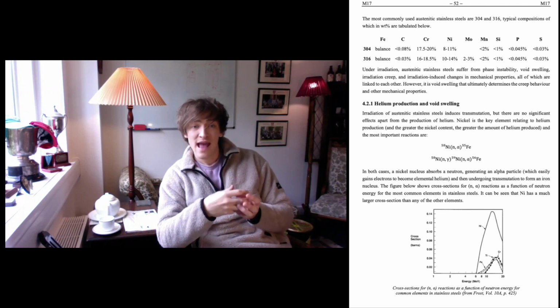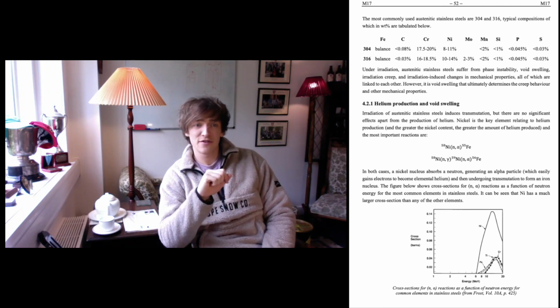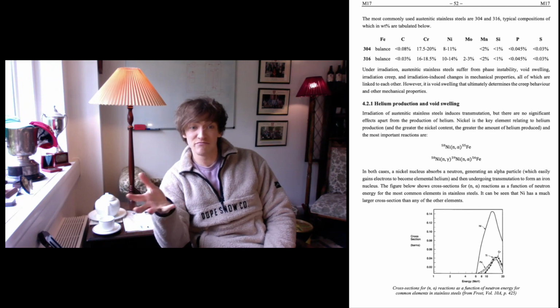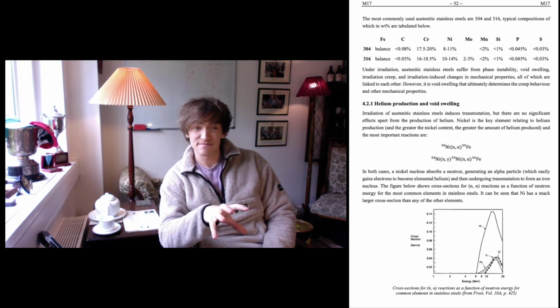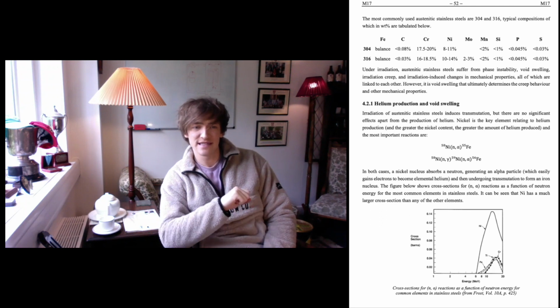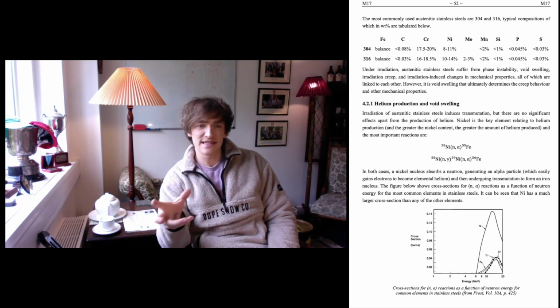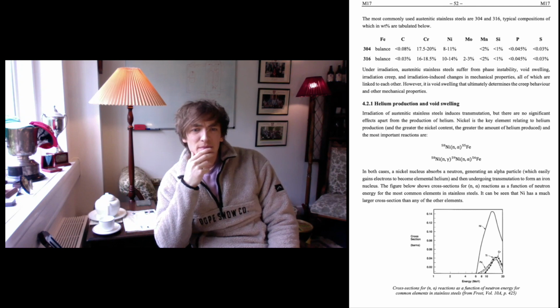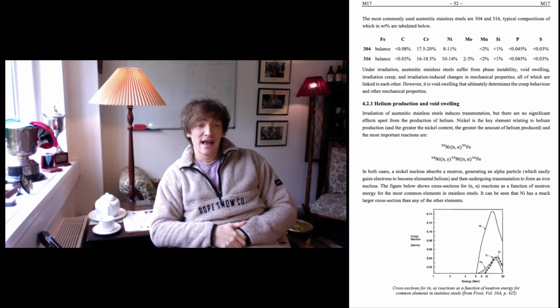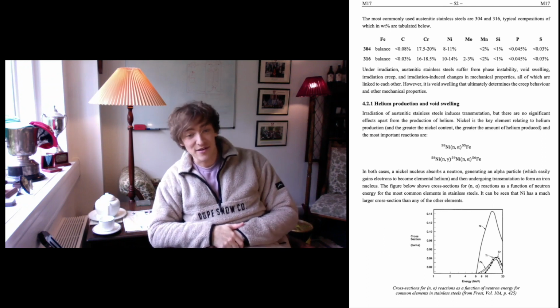elemental helium. And the figure below shows the cross-section for these neutron absorptions and for the alpha emission reactions for those main species in a stainless steel. So you can see that nickel is the biggest worry, as it has a much larger cross-section. And obviously in a stainless steel, there's a lot of nickel.